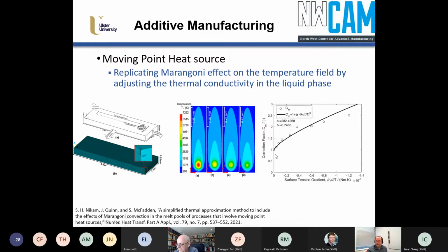Another, simplified way of doing that is to artificially increase the thermal conductivity in the liquid if you're modeling with conduction only. That will have the same effect. That's done quite a lot in the literature, but there's not really much agreement as to what correction factor you should use. So what we did here was model in Fluent with Marangoni convection, and then model in ANSYS using APDL with the conduction code. We modified the surface tension gradient in the Fluent model, and the correction factor for thermal conductivity in the liquid in the APDL conduction model. And we got this relationship, so that's out there now for people to use if they find it useful.